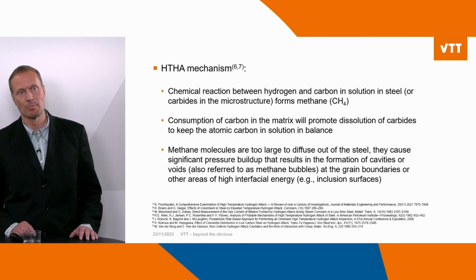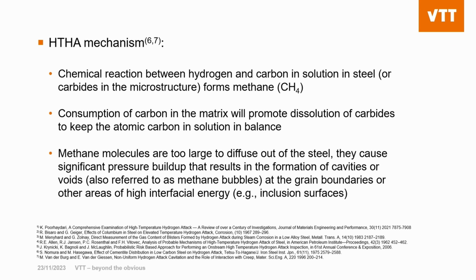The high-temperature hydrogen attack mechanism goes as follows. First, the chemical reaction between hydrogen and carbon in solution in steel or carbides in the microstructure of the material form methane. This consumption of carbon in the matrix will promote dissolution of these carbides to keep the atomic carbon in solution in balance. Now these methane molecules are too large to diffuse out of the steel, and therefore they cause significant pressure buildup that will result in the formation of cavities or voids, which are also referred to as methane bubbles, at the grain boundaries of the material or other areas of high interfacial energy. And these areas of high interfacial energy can be, for example, inclusion surfaces.